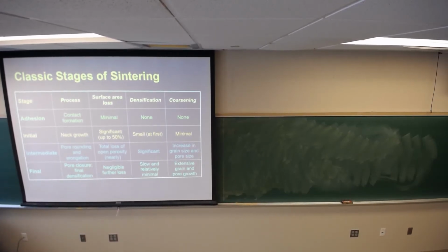Okay, initial stage sintering, very low densification, very high porosity in the body. Okay, but you lose a lot of surface area in the initial stages of sintering. Okay, you form necks in the system. Okay, neck growth, and then densification is small at first, and then if we get into intermediate stage, we start to form pore channels. Okay, we see grain sizes increase and pore sizes increase also, and you eliminate almost all of the open porosity by the end of intermediate stage. In fact, you would argue that all open porosity is eliminated by the end of the intermediate stage, and then at that point you have closed off the pores.